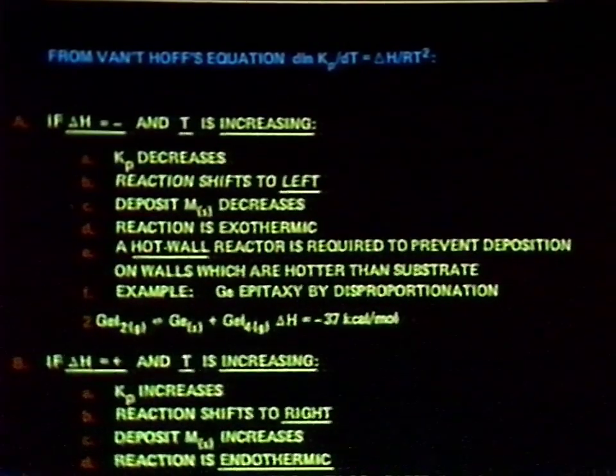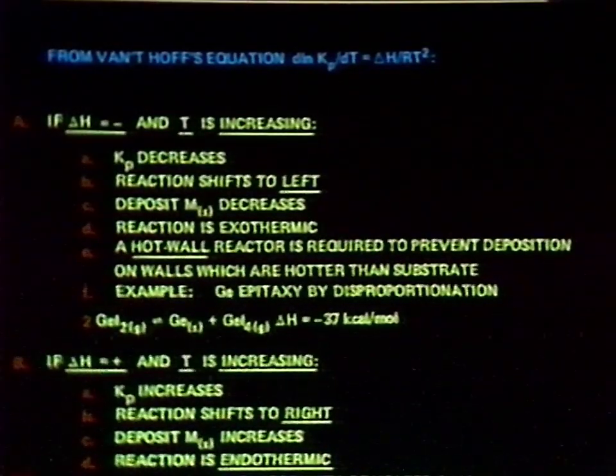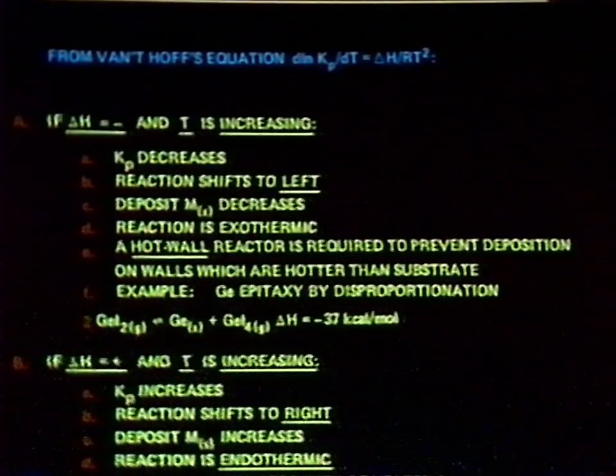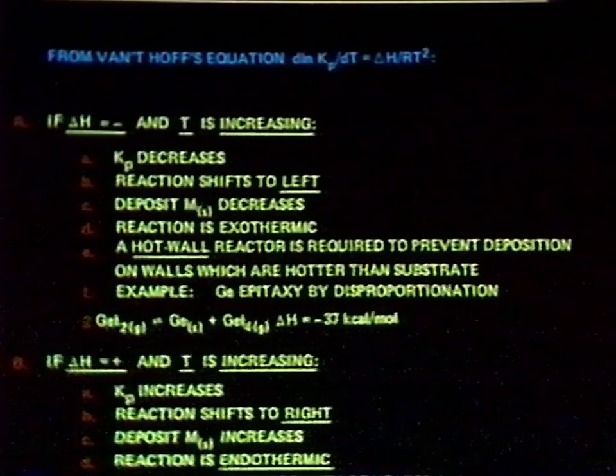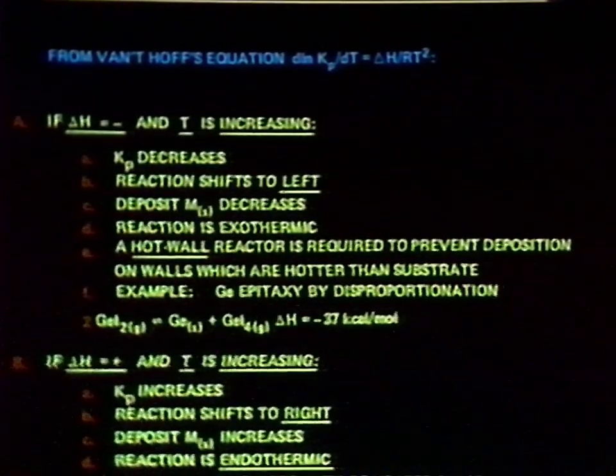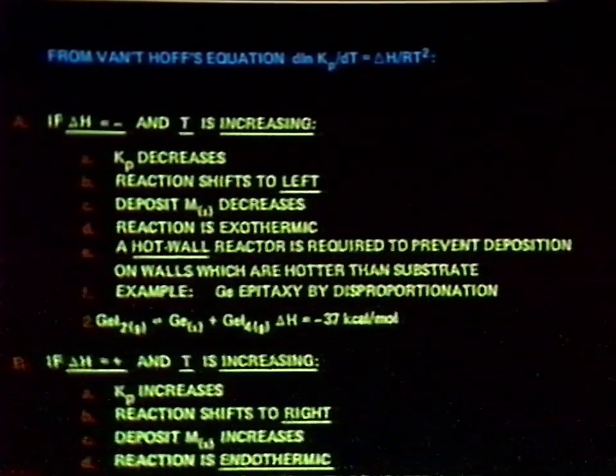Therefore, a hot wall reactor will be needed to prevent deposition on the walls. A hot wall reactor is one like a resistance heater type of CVD system. If it were the opposite, that is, if the wall were water cooled, for example, then the opposite would take place. We would have deposition occurring at the reactor wall rather than on the substrate. An example of this type of reaction is shown here, namely epitaxy of germanium by disproportionation, where germanium diiodide goes into germanium and germanium tetraiodide with a delta H of minus 37 kilocalories per mole.